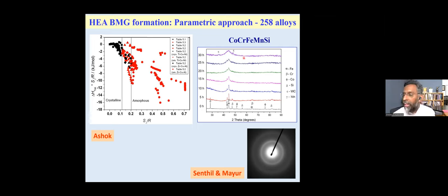How do we know? We see that there is a relation between this crystalline nature and amorphous nature and what is called the strain inside the material. If you add elements together where the atomic sizes of these elements are similar to each other, then there is not much of a strain inside the material. If there is not much of a strain inside the material, it is crystalline. We studied this by picking up some 250 alloys and did a very exhaustive study to find out when do these high entropy alloys remain crystalline, and when do they become amorphous? We found that when the strain inside the material is large, there is a tendency to form amorphous. And that's exactly what we have utilized.